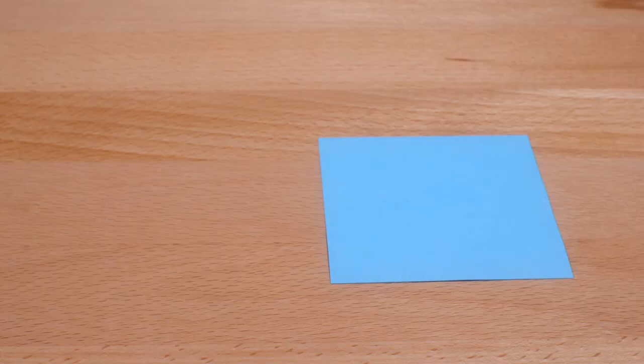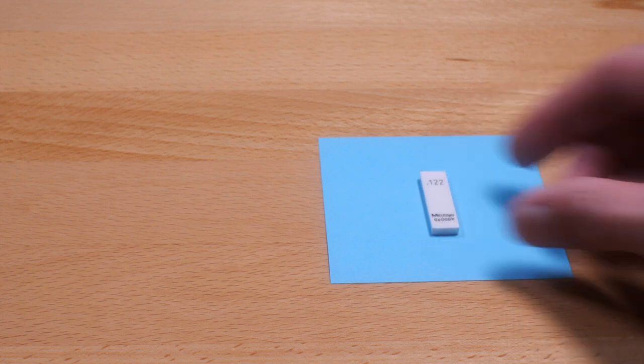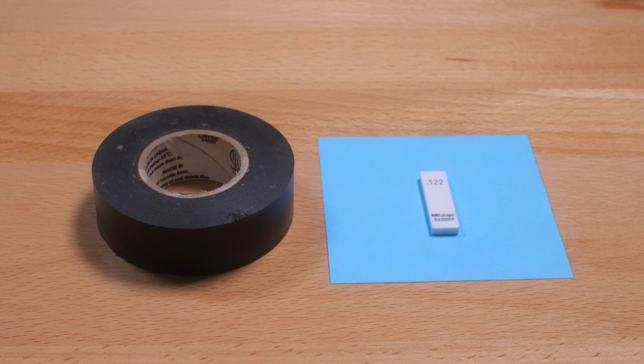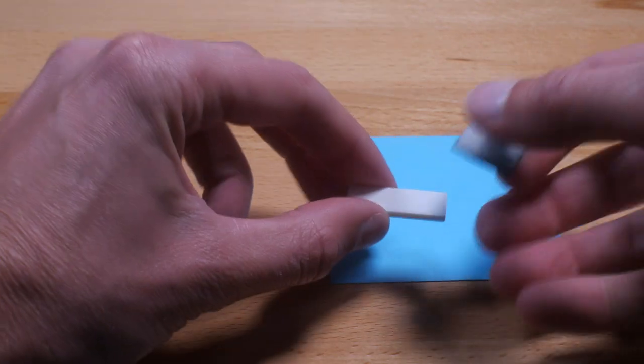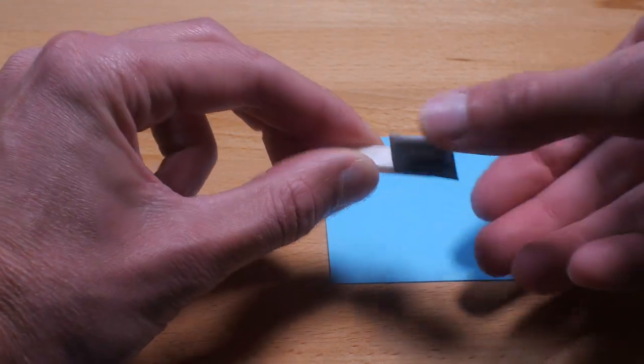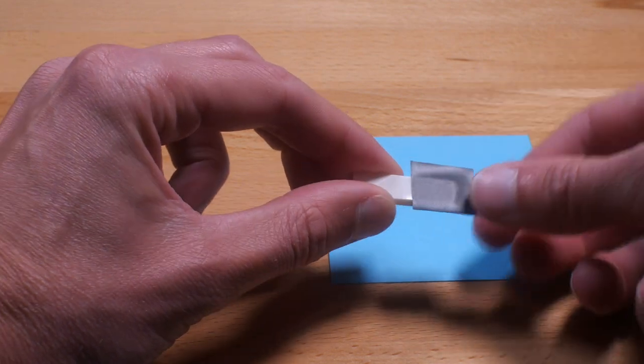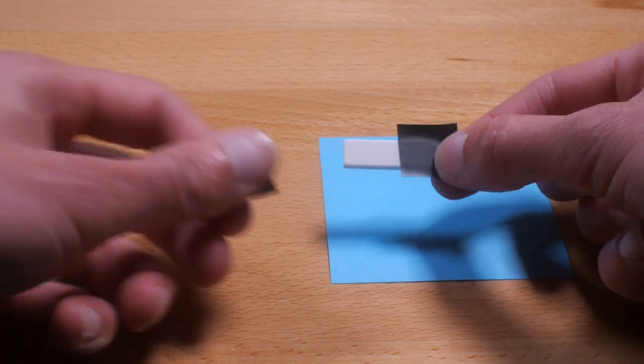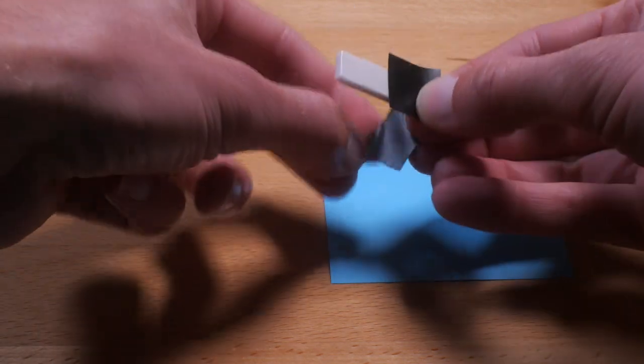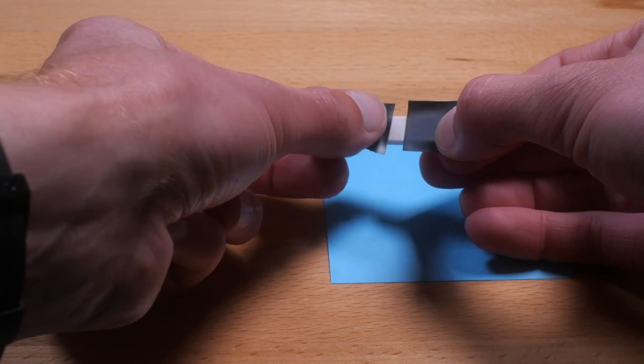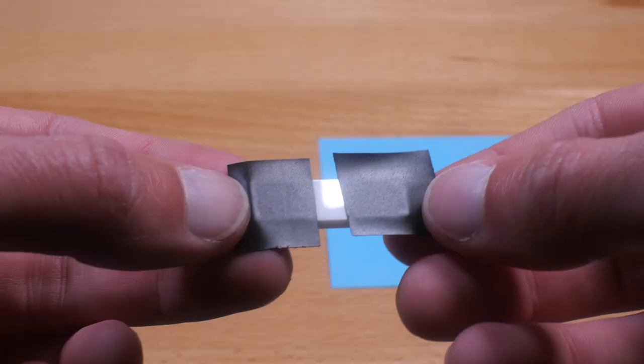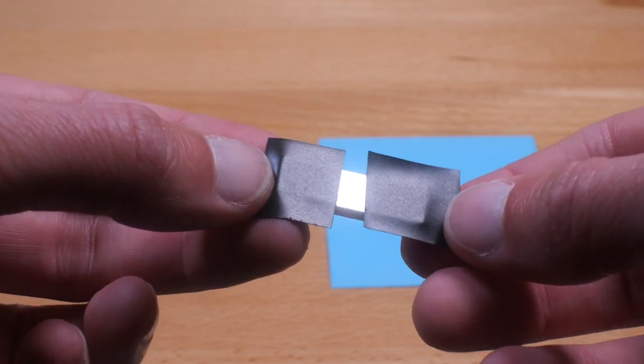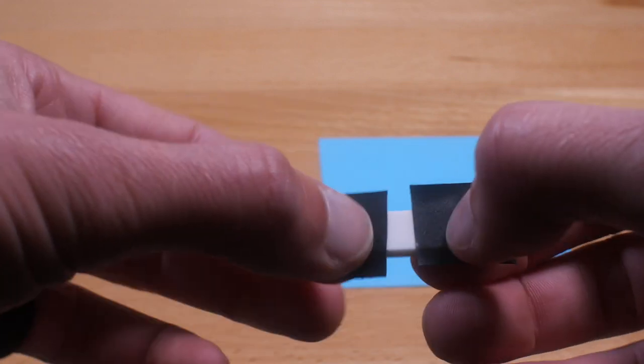Now for the tests. The test specimen I will be using for these tests is a grade zero ceramic gauge block purchased specifically for this purpose. I wanted to use a ceramic gauge block so I can measure thickness of the coating from the gauge block's flat, white surface. Before applying the coating, I masked off most of the gauge block's surface with black electrical tape, leaving only a thin section in the middle exposed. This allows me to compare the coated portion of the gauge block to the uncoated portion after the tape is removed. I chose black electrical tape as my masking material so that the coatings I apply are more visible, allowing me to eyeball how much I've applied and how smooth it is.